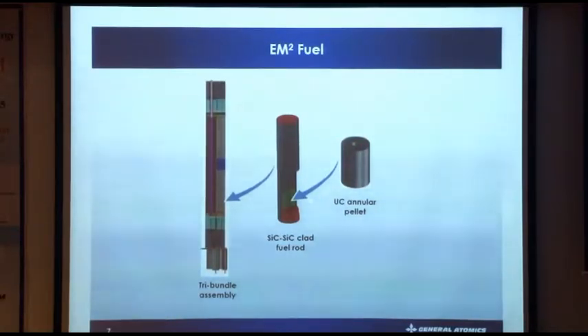These annular pellets are then inserted into the silicon carbide composite cladding. Now, this is another area where we are intensely working, developing the cladding material which can withstand very high DPAs, up to 30 years. And we have some initial indicators from the irradiation test which are very promising. In addition to the cladding, we also need a specific shape. So this geometry, the tubular geometry, is achieved by fibers infiltrated with composite material.